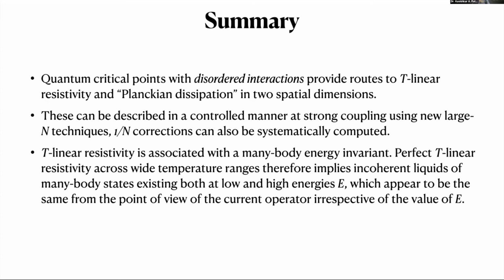One last question. What's the upper limit in temperature where this theory is applicable? Can you conjecture that it can be applicable to very high temperatures? So if you go to high enough temperature, but keep the large N construction exact, what eventually happens is your self energy becomes so large that it exceeds the bandwidth, and then you go into this locally critical regime. So there is a scale for when that happens, and then it's not T-linear unless you do some fine tuning and other stuff.